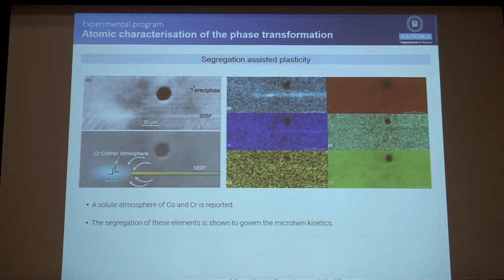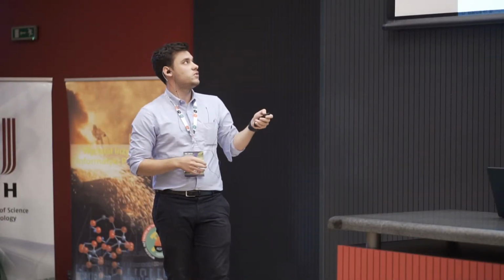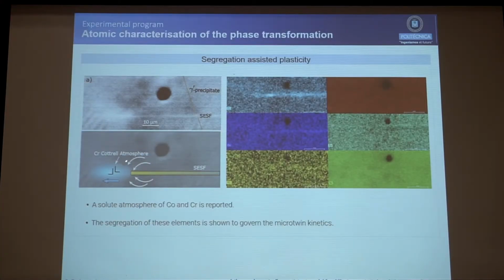There are studies in the literature that show that cobalt and chromium lower quite a lot the stacking fault energy and the antiphase boundary energy of these kinds of faults. So our theory is that as the dislocations are moving forward, creating these faults, they need to segregate new concentrations of cobalt and chromium to eliminate these high-energy structures. And this is what we are trying to model in the next step.